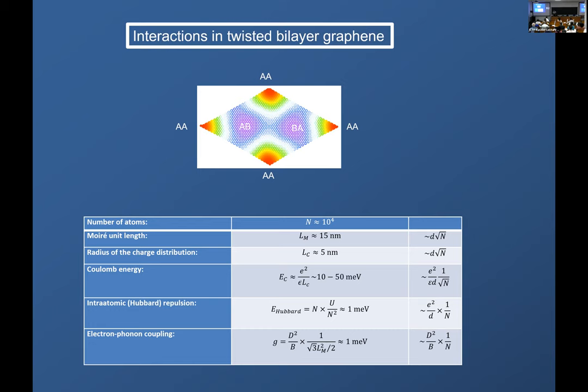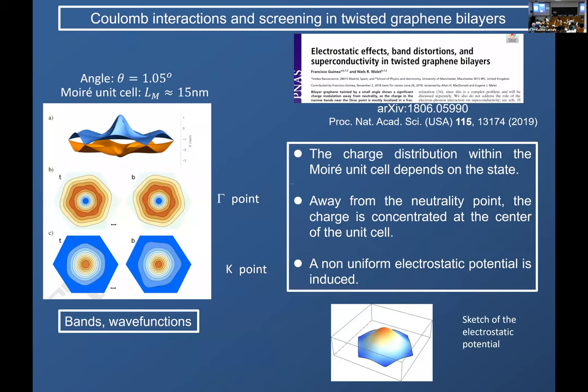All other interactions scale like one over the area of the unit cell. So as a first approximation, the interaction you have to look at first is the Coulomb interaction, the long-range Coulomb interaction, rather than polaronic or intra-atomic Hamiltonians. And now let's do the simplest approximation you can imagine, which is the mean field Hartree calculation. The crucial point is that as you increase or change the charge of the system, you are creating this accumulation of charge at the center of the unit cell. As Ali also mentioned, the energy scale associated to this accumulation of charge is much larger than the bandwidth of the flat bands themselves.